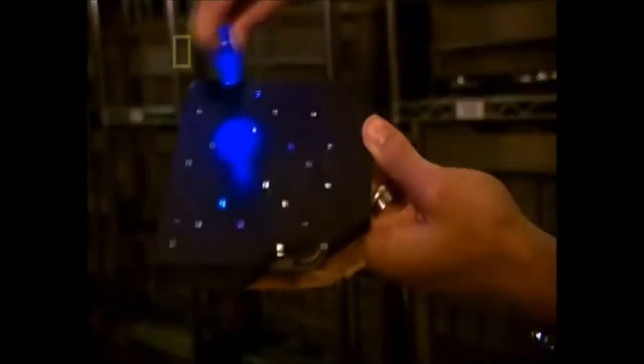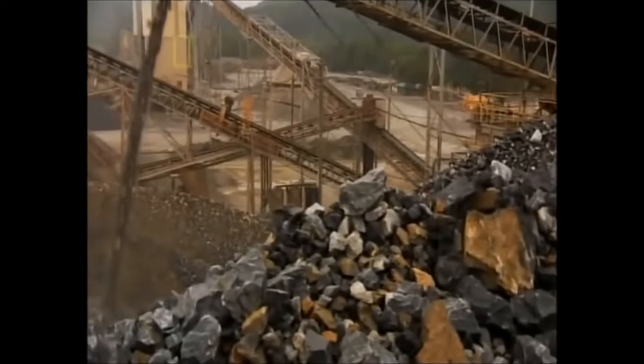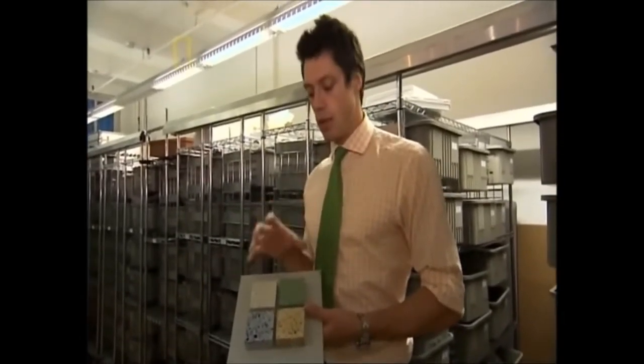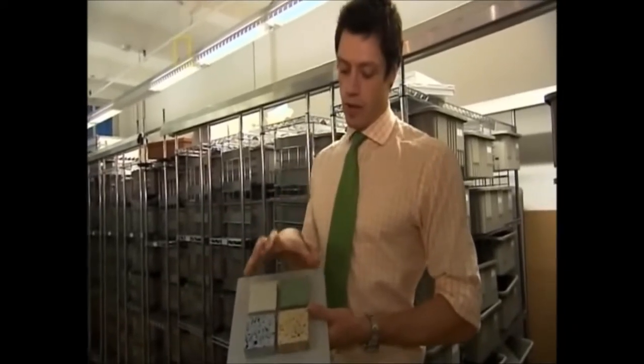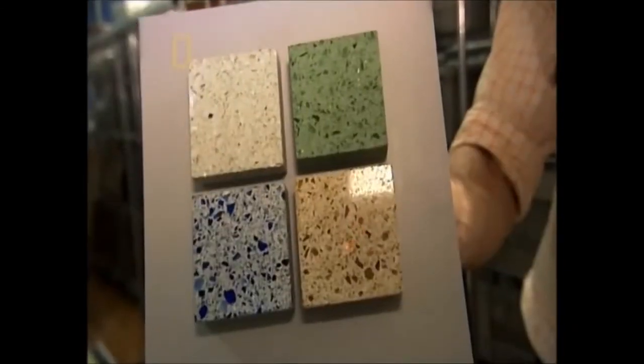New developments in concrete technology now allow for what used to be unthinkable: helping the environment by using an unusual aggregate: glass. The innovation here has been in making sure that the glass doesn't get corroded by the lime in the cement mixture. One of the biggest issues with concrete is that the Portland cement tends to be quite corrosive, and this has been a big problem with things like recycled glass. It tends to corrode and the glass falls out. This composition of cement was actually developed by Columbia University. It is a much less corrosive, more benign cement, allowing you to put the glass chips in. So you can actually now have concrete with glass chips that actually has a good surface effect.